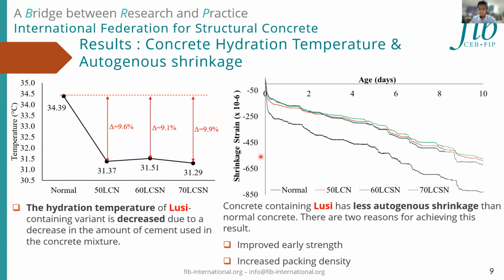Surprisingly, Lusi concrete has less autogenous shrinkage. There are two reasons for achieving this result. First, an improved early strength offered a support in order to restrain the shrinkage. And second, the relatively small particle size of Lusi, calcium carbonate, and GBFS results in a higher packing density.